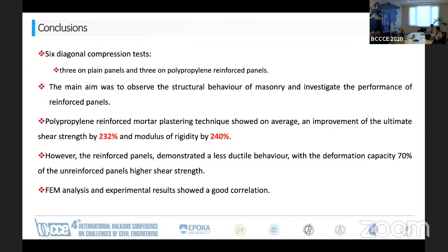And also the model that we developed showed a pretty good correlation with the experimental result, which we believe that polypropylene reinforced mortar coating can be a good technique to strengthen the wall, provided that we do not need, let's say, an increased ductility of the unreinforced masonry.